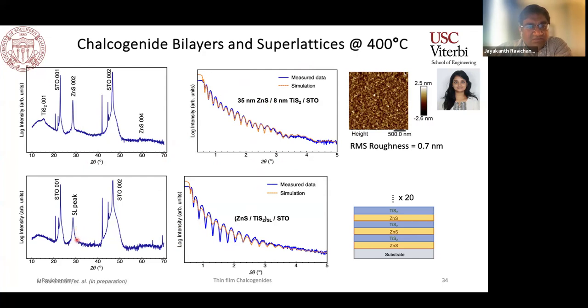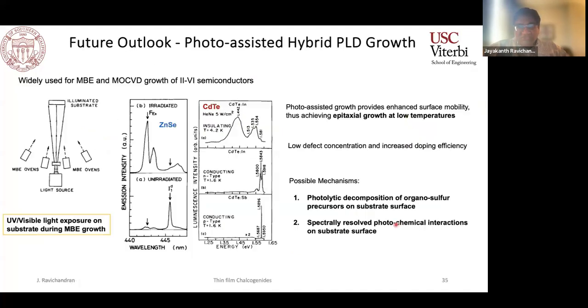It's not as impressive as the oxide systems that we can get in MBE or PLD currently, but this is just the first step towards trying to take some of these materials and show that we can get some heterostructures or bilayers or even superlattices out of these materials. I think we still have a long way to go. We still need better substrates, better control of the surface mobility and reactivity of these materials. We have some ideas to try to resolve some of these issues, but perhaps it'll take a little more work before we can really solve them.